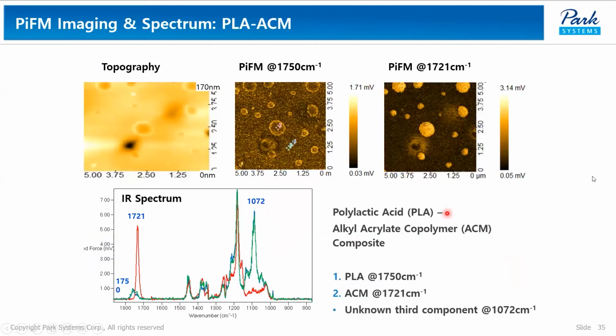With the global attention on the role that plastics play in our ecosystem, many researchers are investigating new bioplastic or biodegradable polymer alternatives to reduce the ecological impact of plastic packaging. One such promising thermoplastic is polylactic acid, PLA. This bioplastic decomposes into lactic acid and can be derived from renewable resources like cornstarch or sugarcane during starch fermentation. PLA is widely applicable, cost efficient to produce, and degrades naturally in the environment under certain conditions. For this reason, PLA is found in many consumer products such as medical implants, 3D printing, and disposable and compostable cups and plates.